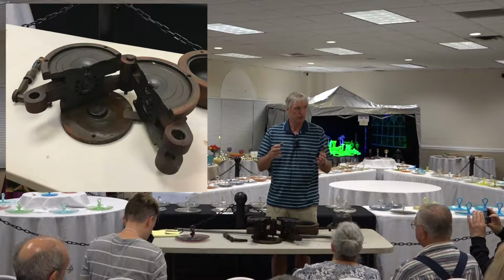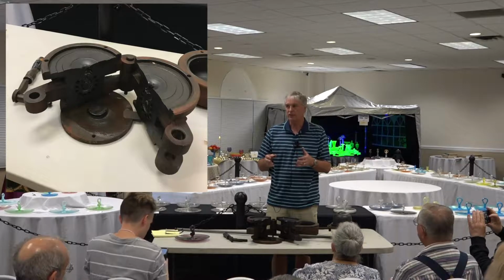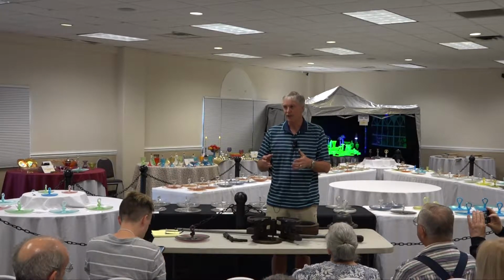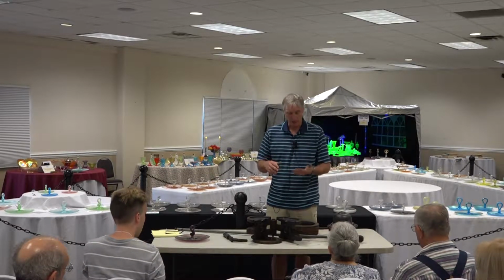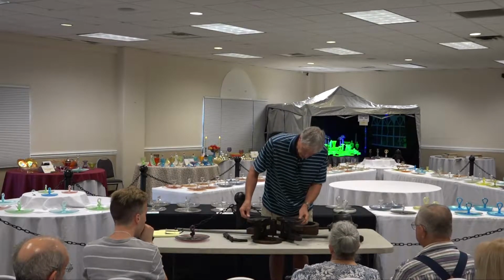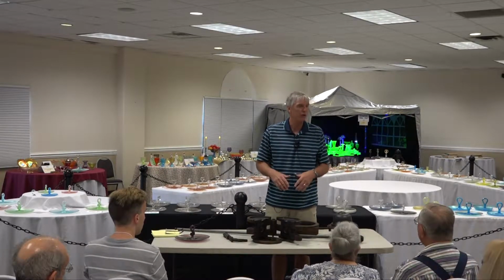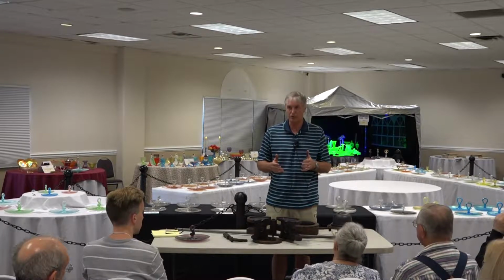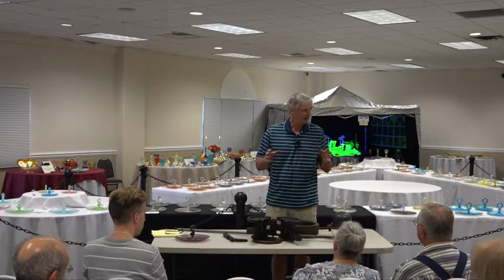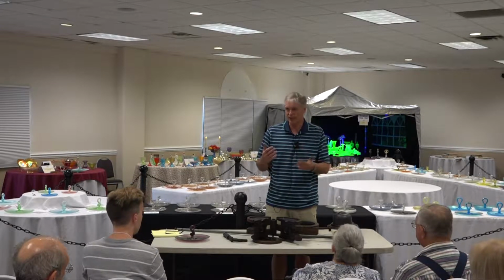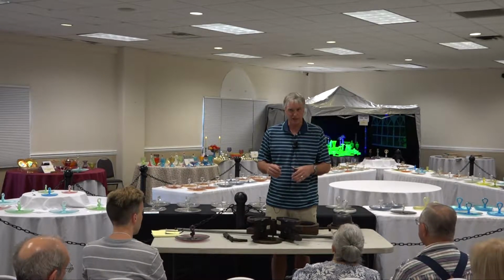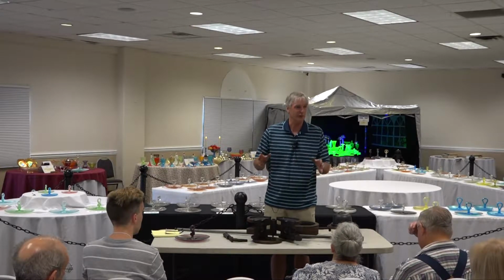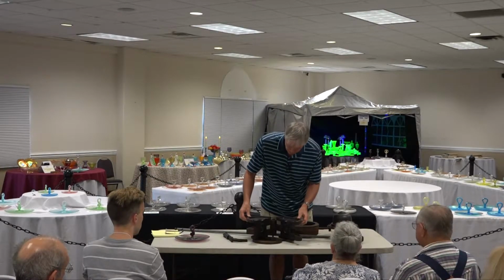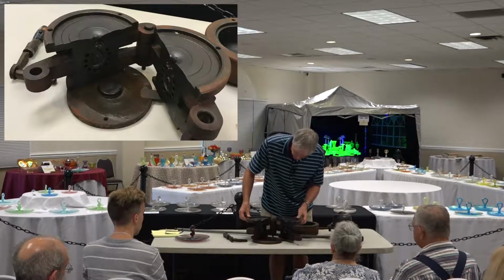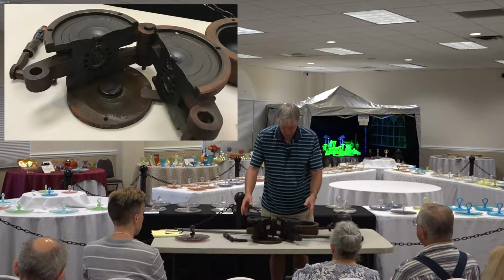And if it runs too cold, the glass will crack when it goes in. It won't flow properly. If it gets too hot, the glass will actually stick. So the mold has to be somewhere in the 800 to 900 degrees in order for the glass to be properly formed and best formed. If it's too cold, again, it'll crack. If it's too hot, it'll stick. And you really don't want it to stick, because then it takes a while to get it cleaned off. Then there's a bottom plate on the bottom here, and all this fits together.